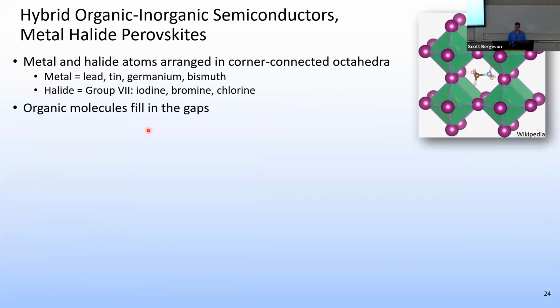Okay, so what are these perovskites? I've used the term hybrid organic-inorganic semiconductors. And here's basically what they look like. You have inorganic atoms partnered with organic molecules. The inorganic atoms are metal atoms, which form at the center of these octahedra, and then halogen atoms or halide atoms like iodine, bromine, chlorine, group 7 in the periodic table, form on the corners of these octahedra. The corners connect to neighboring octahedra. And the organic molecules, in this case methylammonium, form in the gaps in between the octahedra.